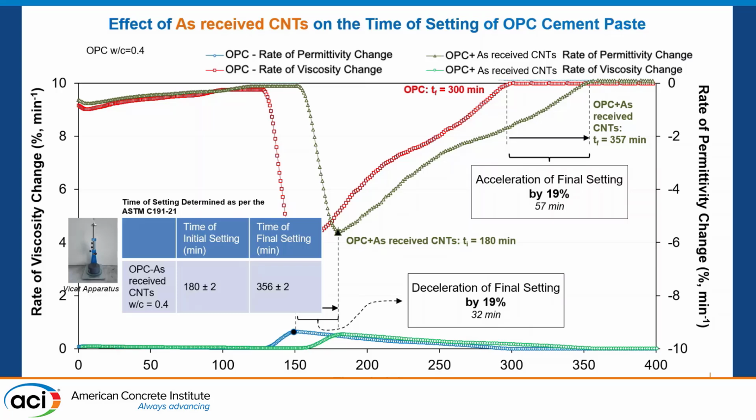So why is that? When we use agglomerated nanomaterials, they act as very good absorbers of electrical energy in the form of capacitors. We know that a capacitor includes electric conductors within an insulating material. When we use agglomerated nanotubes, then we actually introduce these large-size capacitors able to absorb electrical energy.